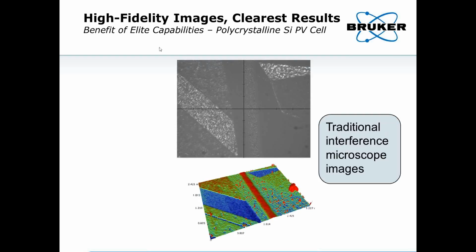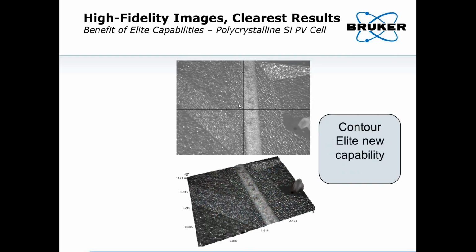A similar example here, you have a polycrystalline silicon photovoltaic cell, and you can see a height map. There's a reasonable view of what's happening on there, but again, with the elite capabilities, you can bring out a lot of the new nuances and texture of the surface in greater detail, and then make the same kind of a height measurement with that true image overlay onto the three-dimensional data that you would typically do with a pseudo color overlay.